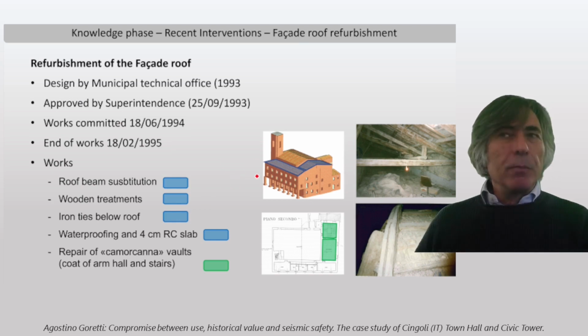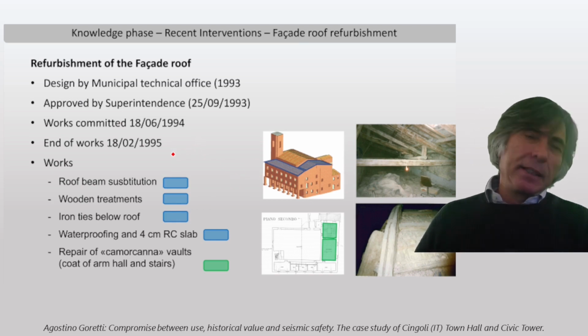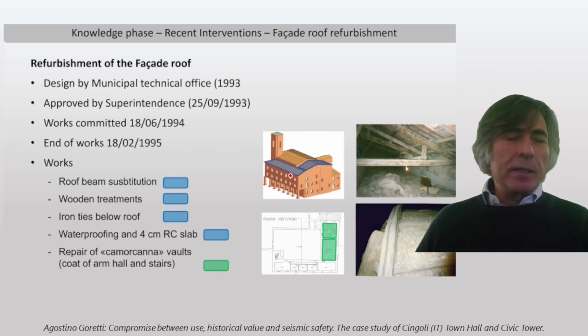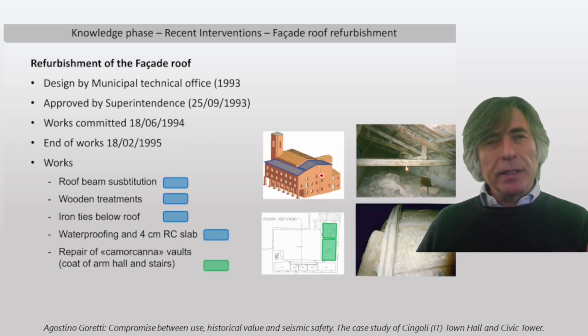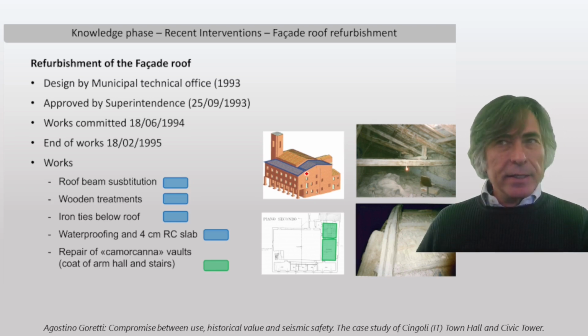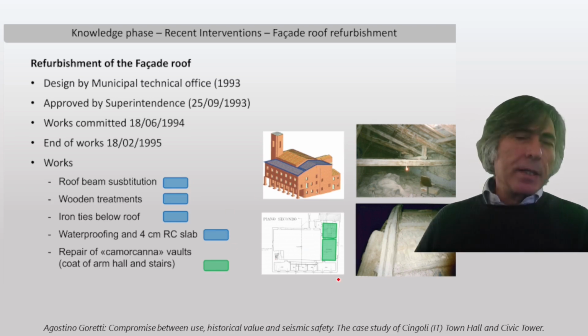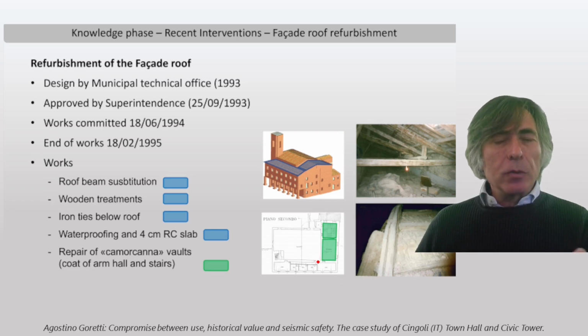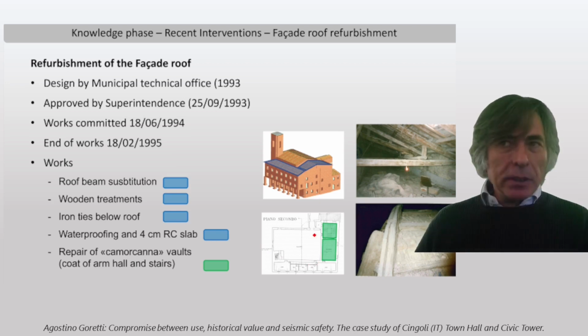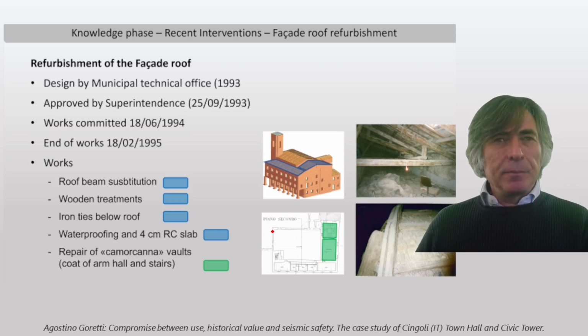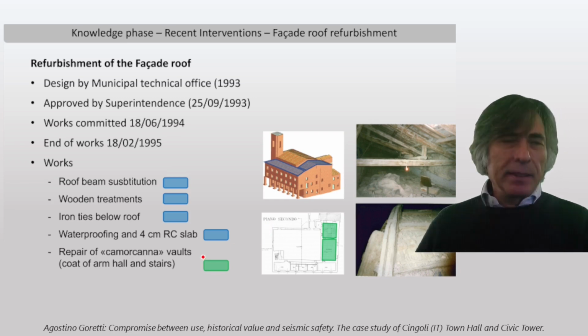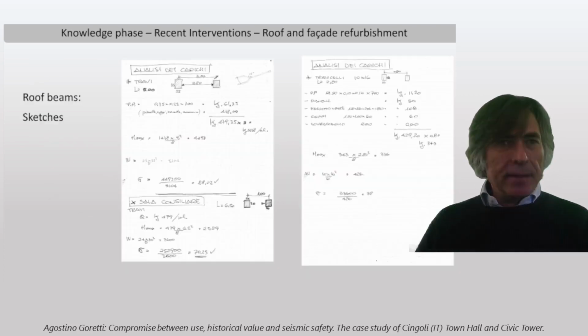After that, there was the refurbishment of the facade. In that refurbishment in the mid-90s, basically there was a substitution of the main elements of the wooden roof of the highlighted part in the picture, over the facade and over the coat of arms room, hall and internal stairs, and also some intervention on what we call camorcanna walls, the walls that are made with bamboo and some mortar, that are quite rigid and brittle, I would say. These elements can crack immediately, and since they are frescoed on the interior part, they were strengthened with some additional elements and some resins.